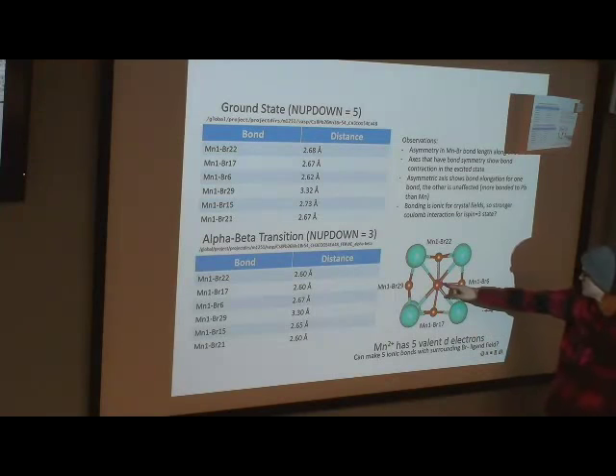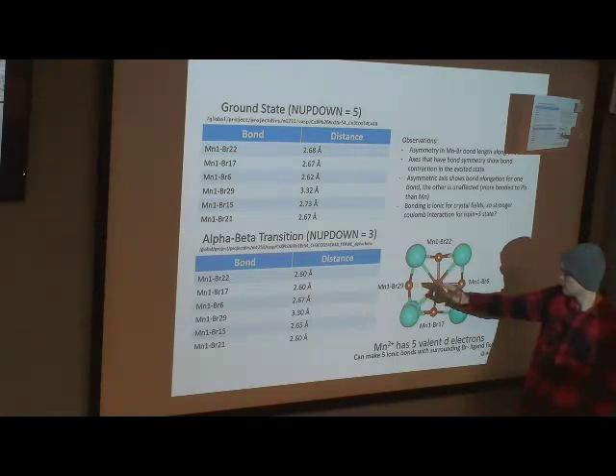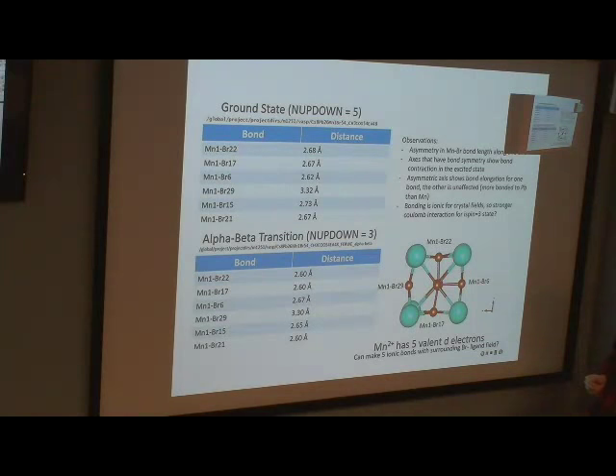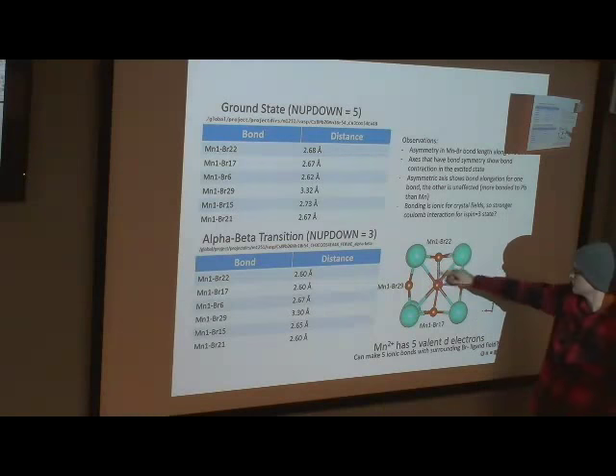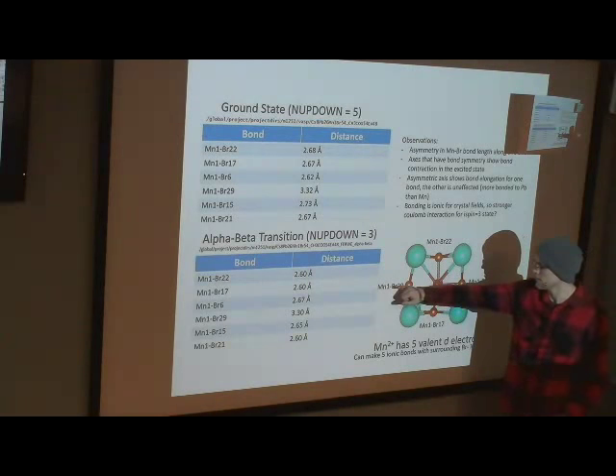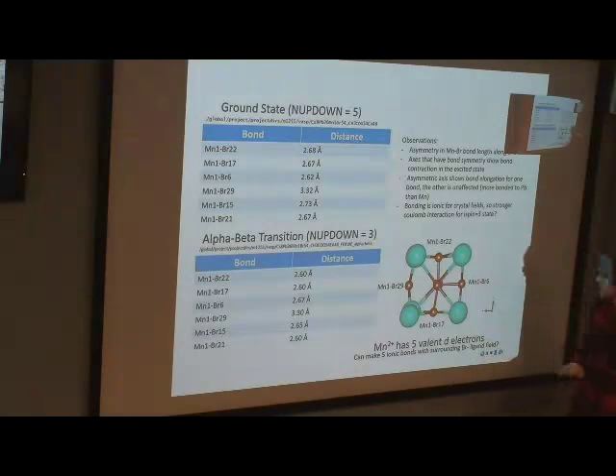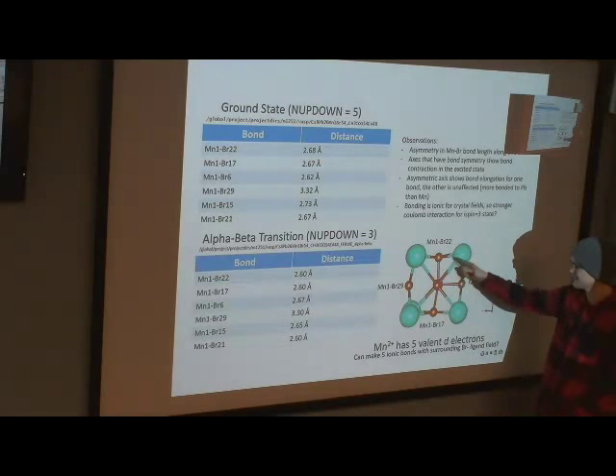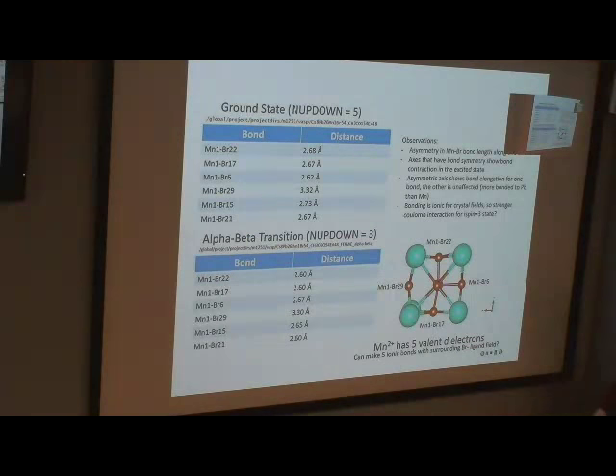And the one that elongates is this one here, an asymmetric bond, because it looks like the dopant is bonding to only 5 of these ligands, and this bromine here is more attached to a lead that's hanging out over here. If you just think of general chemistry, manganese 2+ has 5 valence electrons, so you'd think it would make 5 bonds. That's how I rationalize that it bonds to 5 of the bromines and lets one of them hang out by the lead.